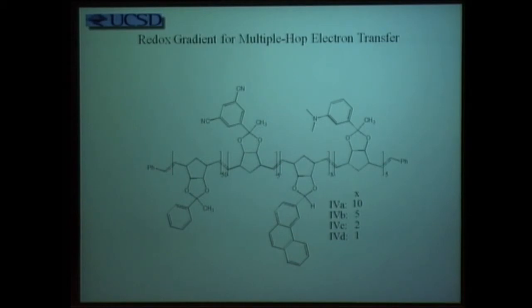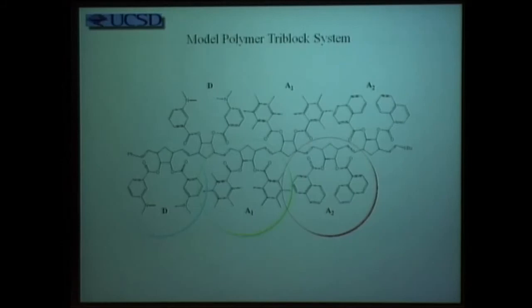It's really quite interesting to find out ways in which this absorptive interaction can take place in a whole series. And here, for example, is one where the backbone is made by opening up of a norbornene unit. So what you see with these polymers is that by combining different polymers at well-defined sites, you can predict almost exactly what absorption characteristics evolve and can provide the criterion that would result in very efficient photosensitization.